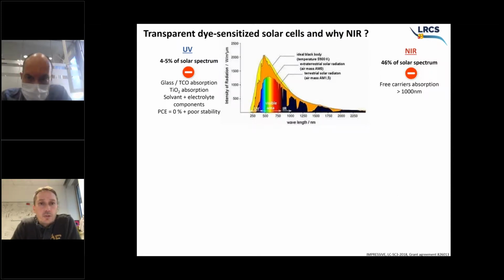So making a transparent dye solar cell is possible. The choice was whether we go for the UV or the near infrared. So it's very easy to understand why we went to the near infrared and not the UV. The first is because UV takes into consideration only 4 or 5% of the solar spectrum. But not only that, it's because also in the UV, the glass and the TCO are strongly absorbing.